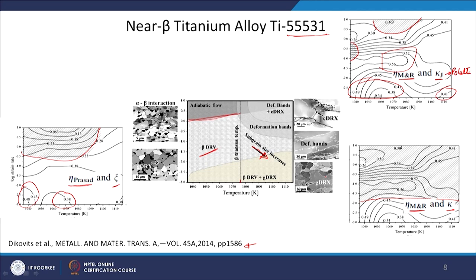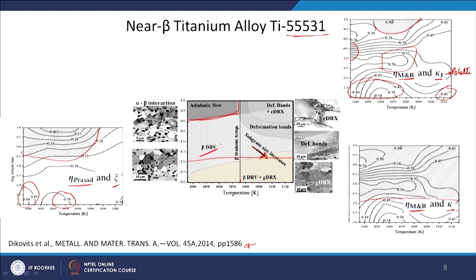Comparing the models with the microstructure, the DMM model is able to predict instability in the top region, matching some parts, whereas the modified DMM shows instability over a very large range not fully supported by microstructure. So the modified dynamic materials model is more conservative than the other models. For efficiency, dynamic recrystallization is seen in areas of higher efficiency in all cases. Efficiency-wise, both DMM and modified DMM are able to predict areas where dynamic recovery and dynamic recrystallization are observed.